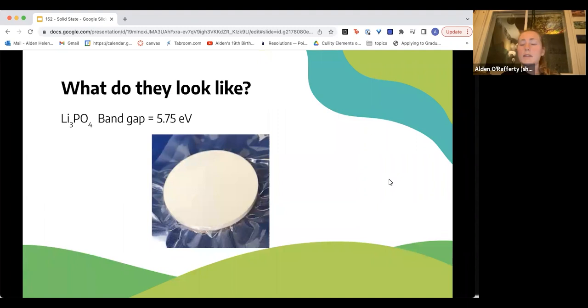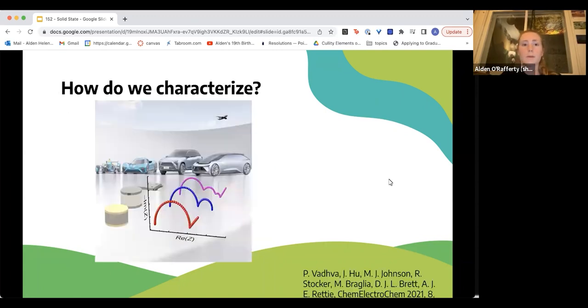And to gut check that against other concepts we've learned, what they physically look like. This is a slab of, there's a little bit of lithium phosphate, and its band gap is 5.75 electron volts. And sure enough, it looks white. So most solid electrolytes look clear or white, and this is because they have a really large band gap, meaning they're absorbing mainly in the ultraviolet range, and reflecting other things. So what we're seeing is what it's not absorbing, which is the whole visible light spectrum, essentially, which is why it looks white. So that checks out.